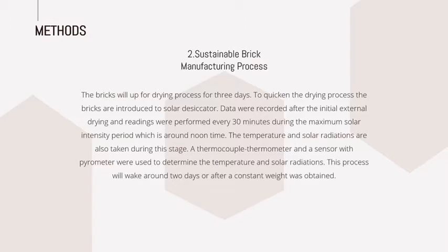Data were recorded after the initial external drying, and readings were performed every 30 minutes during the maximum solar intensity period, which is around noon time. The temperature and solar radiation are also taken during this stage. A thermocouple thermometer and a sensor with a pyrometer were used to determine the temperature and the solar radiation. This process will take around 2 days or until a constant weight is obtained.